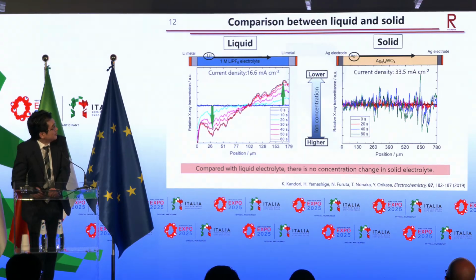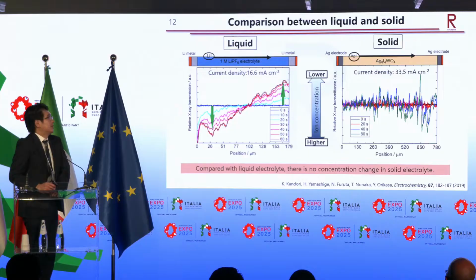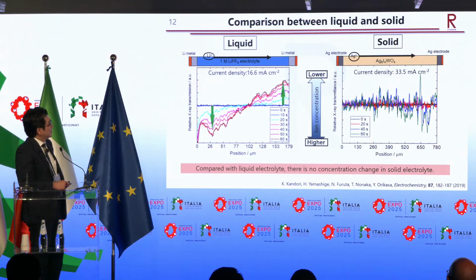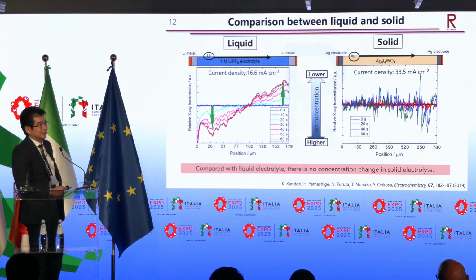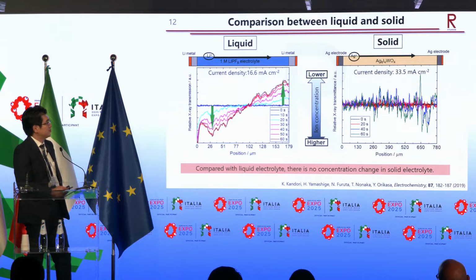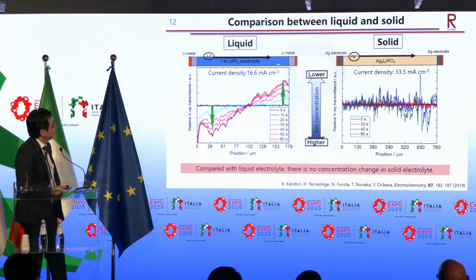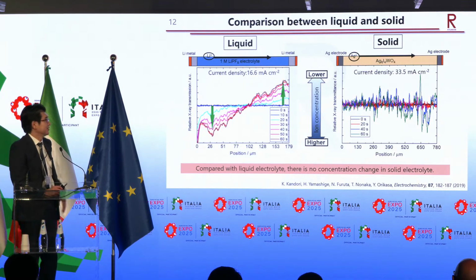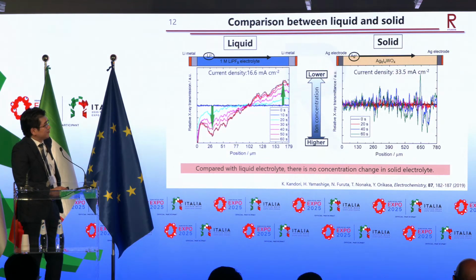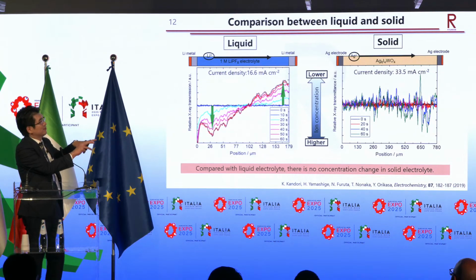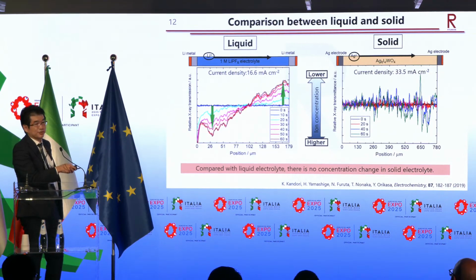So this is a comparison of the liquid-type lithium-ion battery case and the all solid electrolyte case. The left shows the liquid electrolyte, and the y-axis corresponds to the concentration of the PF6 anion. Supposing charge neutrality, the same concentration distribution occurs inside the electrolyte. So during lithium-ion deposition on this side, the concentration is also changing. However, for the solid electrolyte, there is no concentration distribution here, only a change of shape due to the silver deposition on this side.